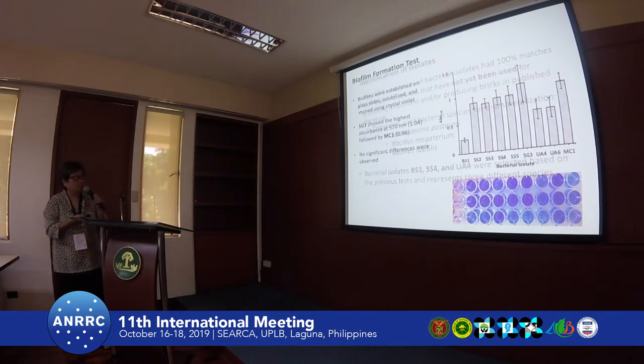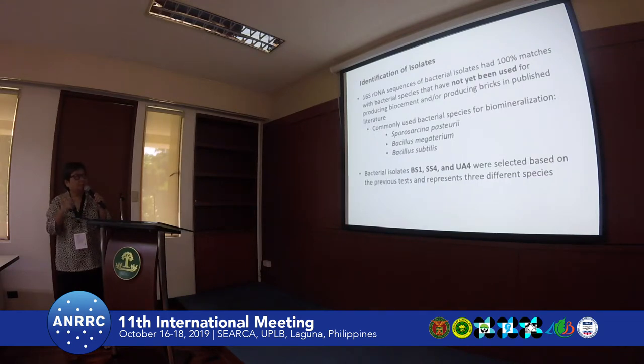So from these results, we were able to identify our best isolates. They come from the genus Viridibacillus. The most common bacterial species used for biomineralization are Sporosarcina pasteurii, Bacillus megaterium, and Bacillus subtilis. So the literature you will find are on these three species. However, Viridibacillus has not yet been used for the study of bacterial bricks.